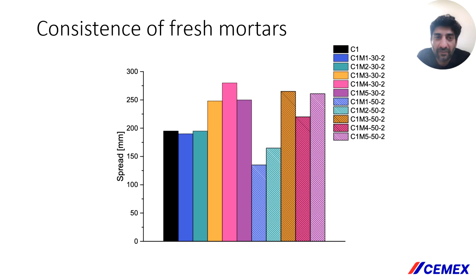Using these fixed superplasticizer dosages of 1.1 and 1.5 weight percentage highlighted notable differences in consistency for the 30% and 50% calcined clay blends, respectively. In fact, an increase in consistency was observed for blends containing calcined clays of the Lias group, as highlighted by the flow table spread measurements.